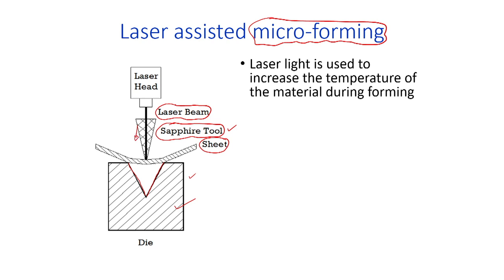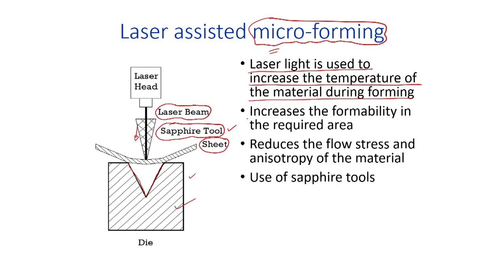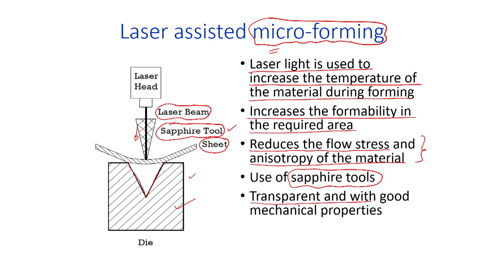It's very similar to the way we saw in our previous class. It is laser assisted material forming, but for micro level application. Laser light is used to increase the temperature of the material during the forming application. That heating enhances the formability in the required area, and that formability enhancement is nothing but reduction of flow stresses and anisotropy of the material, which leads to generation of the micro features. Here we are using sapphire tools, which are transparent and have sufficient strength. Sapphire tools have good mechanical properties and are transparent. Moreover, sapphire tools have a high melting temperature.